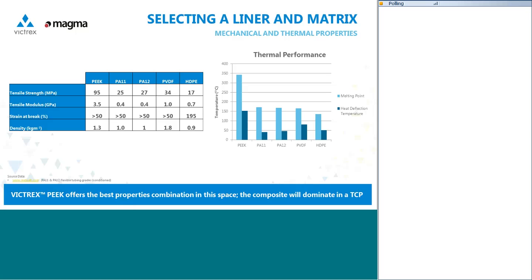Now, this isn't to say that any one material is ideal for any particular application. This is very much a case of you choose the appropriate material for your application. And there will be applications where clearly something like a HDPE will be more than adequate. I think the key takeaway is really that the PEEK material is very high strength, as you can see, something like 3 times higher tensile strength than the next nearest material. It is of course stiffer, but in a composite at least, that extra stiffness is dwarfed by the stiffness of the carbon fiber, which is a common feature in all of the polymers you can see. Strain at break in all cases is greater than at least 50%, and depending on what you're comparing with, density, there's not a lot in it really between all the materials.